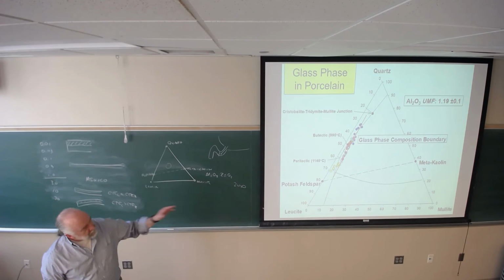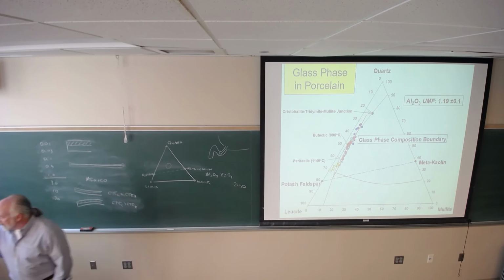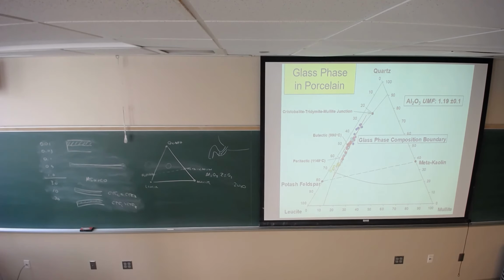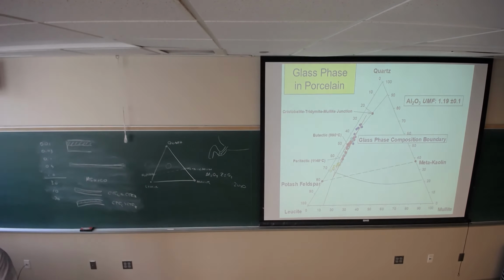But this composition boundary is a big deal. So we can then predict exactly how much mullite will form in a porcelain body, because the amount of mullite that forms is the amount of alumina left over after the alumina is in the glass phase. Okay? So if I have more alumina than I need to saturate the glass, I form mullite. And I can predict exactly how much mullite I'm going to form in the system, which we'll talk about later.